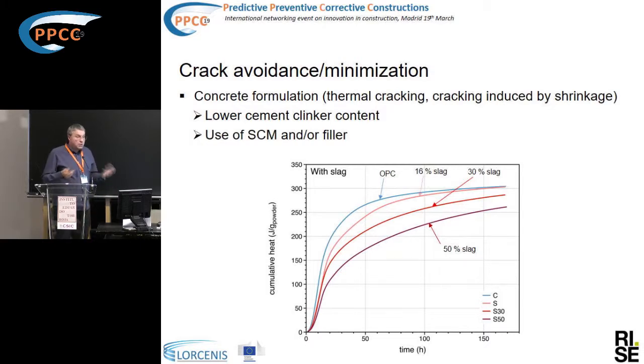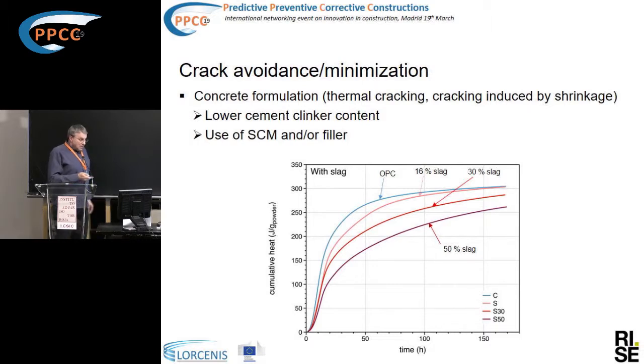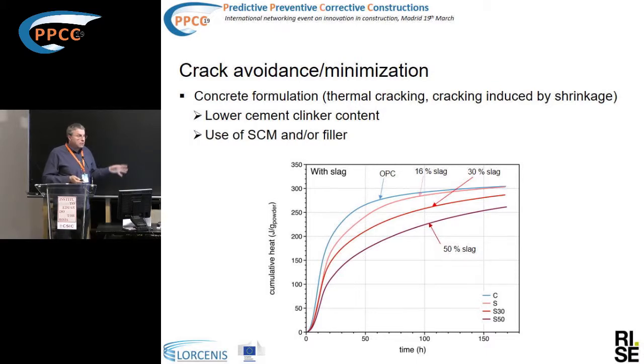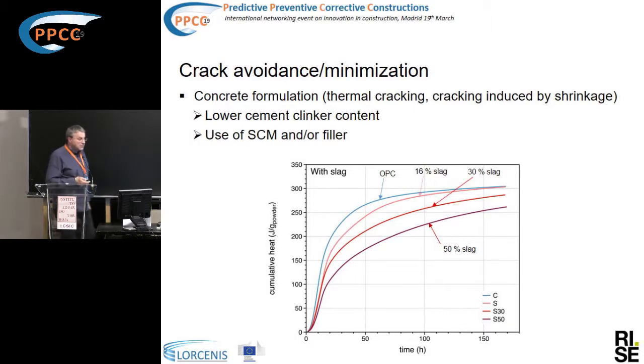By reducing clinker content you can avoid temperature-related cracking, which is also done for massive structures. They usually have a low cement and clinker content, and often use supplementary cementitious materials or rock fillers — or both — to limit the maximum heat of hydration.